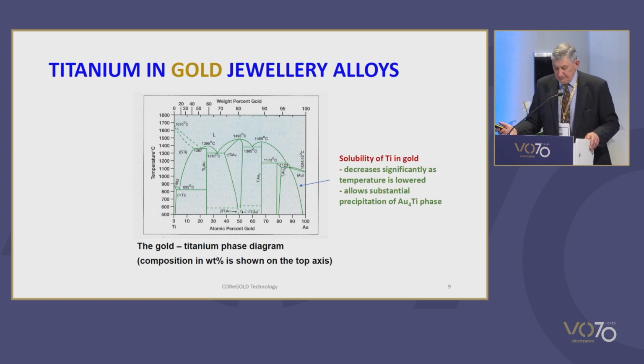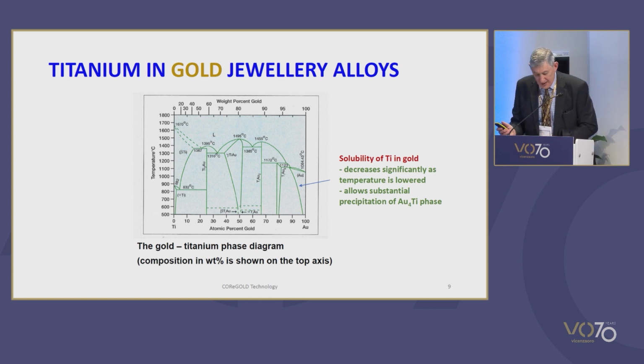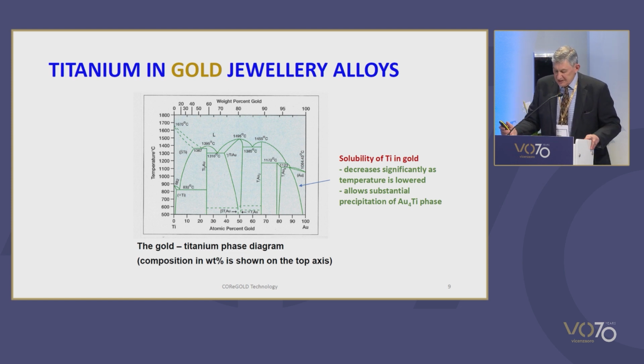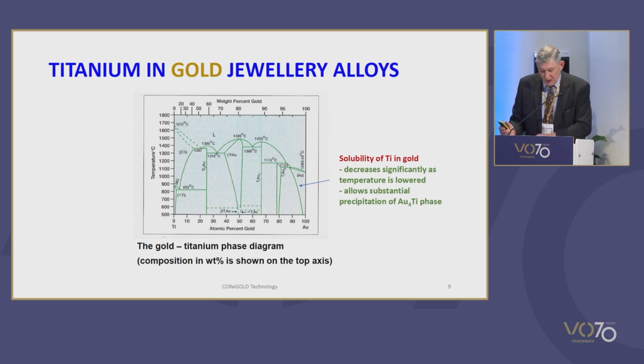The phase diagram, and I apologise for those of you that don't like phase diagrams, but it does show the limited solubility of titanium in gold at the low temperatures. The reason for limiting it to a 1% addition was to make the gold hallmarkable as 24 carat. Titanium acts as a grain refiner and makes the alloy age hardenable.